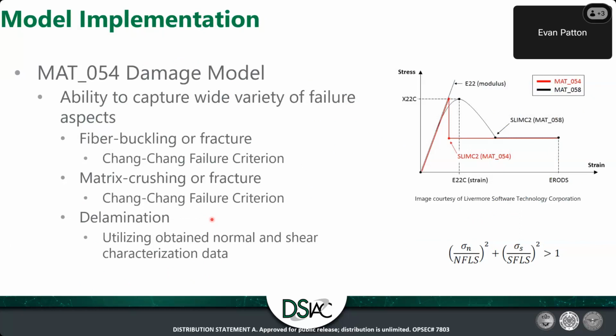As mentioned earlier, I utilized LS-Dyna, specifically material card 54, which if you're a composite modeler, you're probably very familiar with. For those of you who aren't, the graph on the right-hand side is a good indication of what's going on behind the scenes. Essentially, you feed it your mechanical data, and there are damage softening parameters such as SLIM C2. You have your linear elastic response, and then you hit the failure limit, which you determined experimentally. Upon hitting that limit, you drop to a percentage of the strength, and it carries load up until a very final failure strain. Once it hits this final failure strain, it completely deletes the element. There's no other load-bearing significance of that element. It's just non-existent and gone.